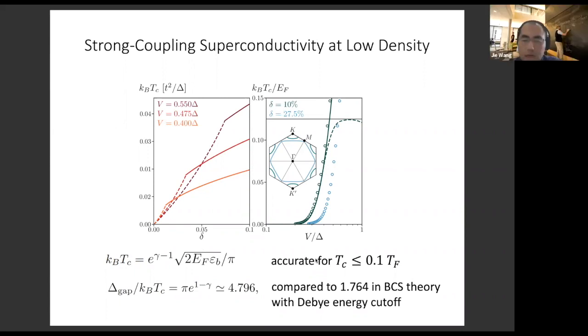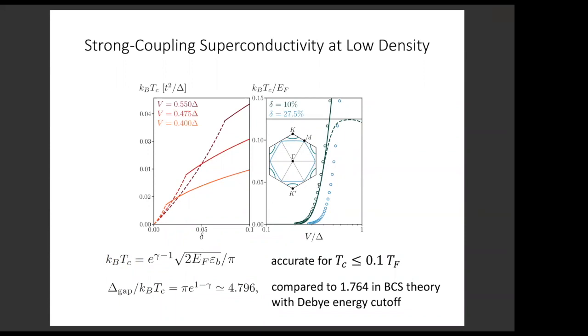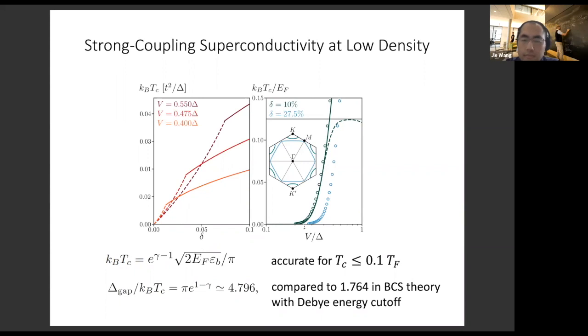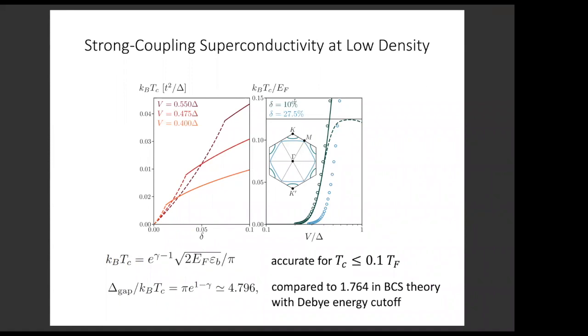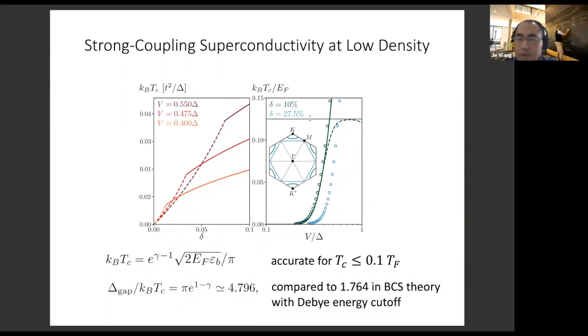Next slide. May I ask one question here? In this figure, is the dot obtained by numerical simulation of T_C over T_F, and the solid line is from the continuum theory? Yes. So the dots are obtained from the lattice mean field calculation, while the solid line is according to this continuum theory prediction. That's because the continuum theory is only developed for the region near K and K prime. So that's why there's no continuum theory for the red and blue dots. Exactly. And this line is the bound.